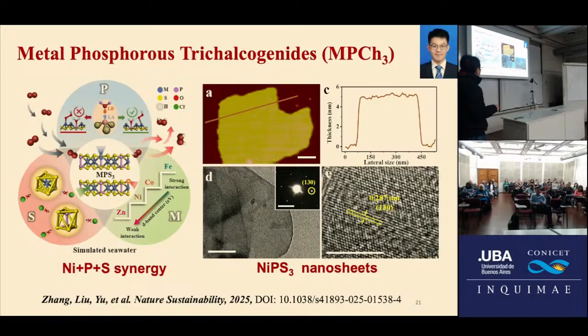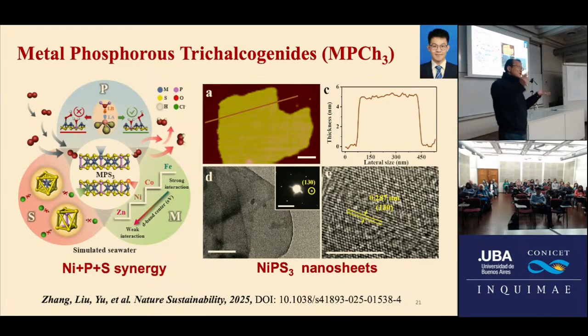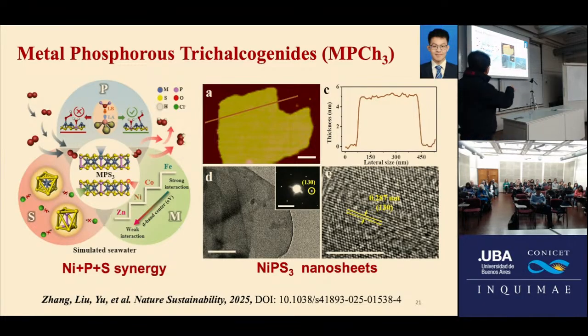So this is the motivation. To do so, most MOF materials are not stable under seawater conditions due to the high ionic stress and the corrosion problem. So here we demonstrate another catalyst, which is a metal phosphorus trichalcogenide with nanosheet morphology. The thickness is around 5 nanometers. What I want to highlight is that in this catalyst, each element, the metal, the phosphorus, and the sulfur, has a unique contribution towards the final performance. I will tell you in more detail.